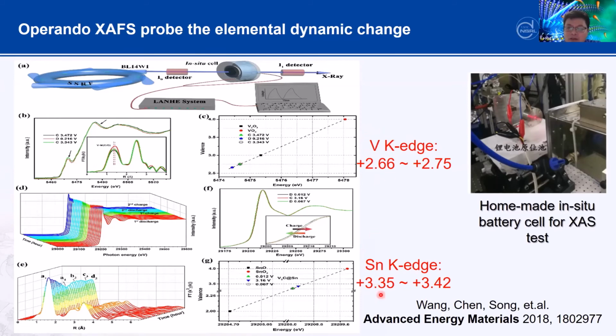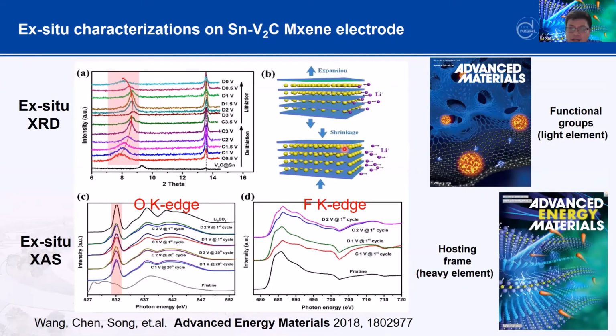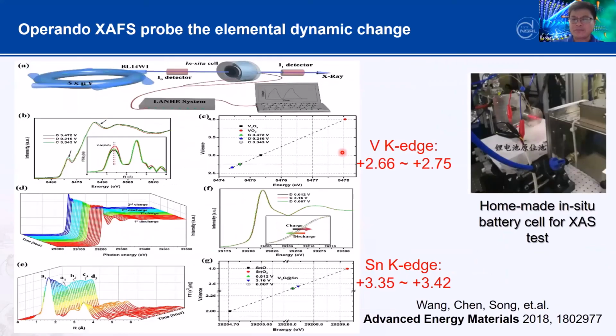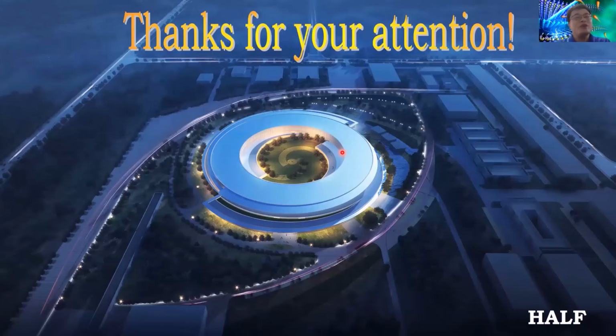This is the vanadium carbide. So for the tin, if you look at this, you will see clearly during your scanning that the valence value can change from 3.35 to 3.42. So this is the average valence. So you really can give the conclusion that during the charge-discharge process, in the hosting materials, the metal contributes to the lithium storage. And meanwhile, the atom and also the functional group contribute to this performance. So I think this is what I wanted to tell you in the third part.